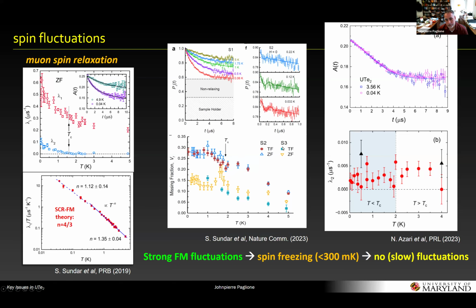Now, I should note that this was seen in both samples that had a larger residual heat capacity and a very small residual heat capacity. Now, the latest experiments use salt flux crystals from the Los Alamos group, and they claim to see a much lower spin relaxation rate, and also nothing that happens through TC. Okay, so these are three different papers, three different results, and it's not really easy to say how they relate to each other. I have my own speculations about what's happening, which may have to do with uranium vacancies and so on, but I'll save that for discussion. Okay.